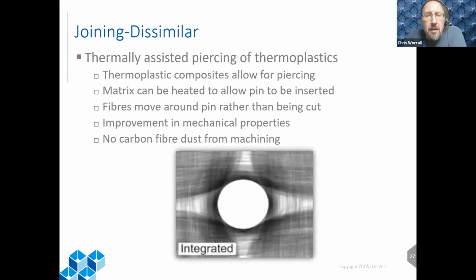Okay, this is an example here of a slightly unusual application. We know that the fibers in the composite carry the load, and so we're often very careful to maintain the fiber length and to put them where we want to. And then we join by mechanical fastening, where we drill a big hole in the composite, cut the fibers, and suffer the consequences, which can mean an inefficient joint with additional weight.